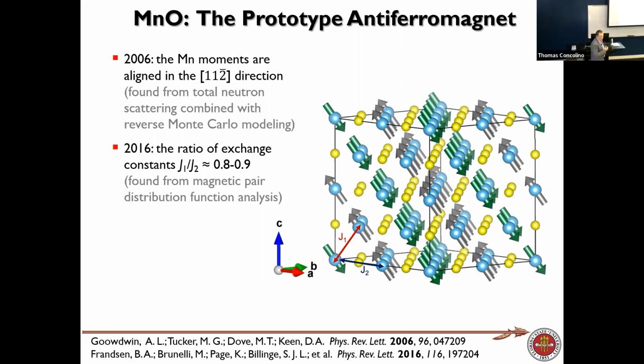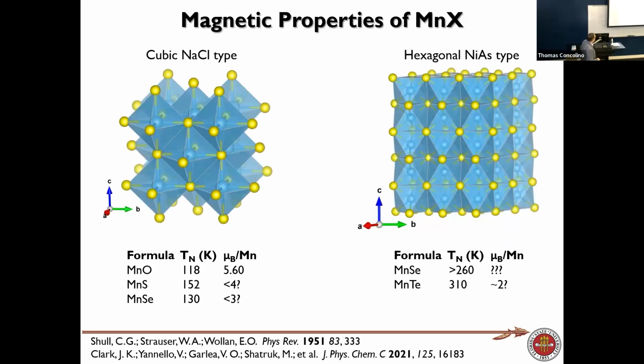And when we approached this problem, the reason we wanted to do it was that we were studying more complicated ternary, quaternary manganese chalcogenides, and we had some observations that magnetic moments were quenching by manganese sulfur and manganese selenide bonding, which we thought was due to covalency. And then I asked my student to just look at binary chalcogenides as reference materials. And when he did that, he discovered that there are a lot of conflicting reports about magnetic moments of manganese sulfide, manganese selenide, manganese telluride. And so we just decided to re-examine the magnetic structure of these materials to have reference points. So we asked Oak Ridge to give us a couple of days to study three magnetic structures. That's where all the story starts.